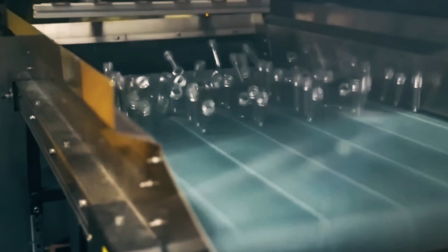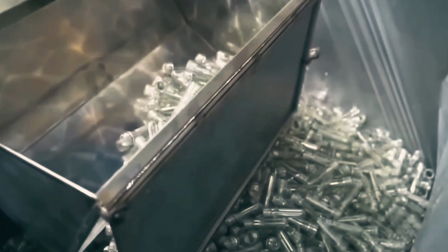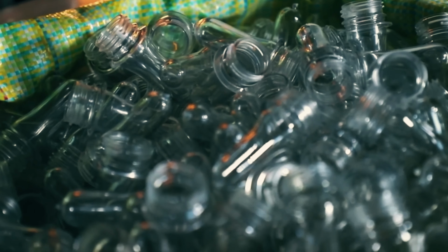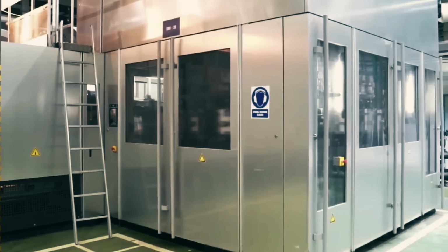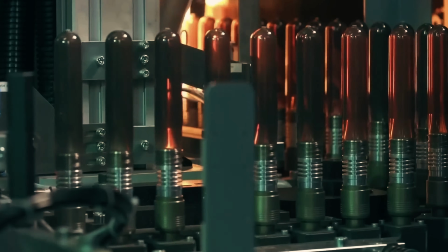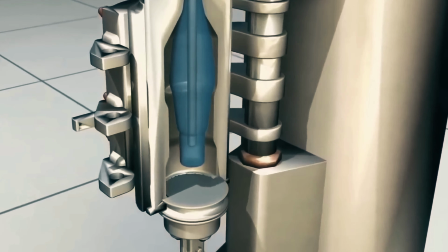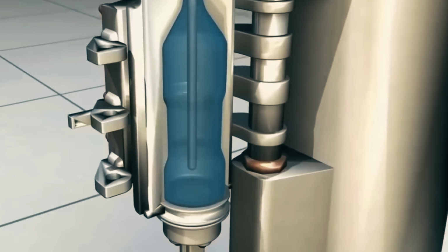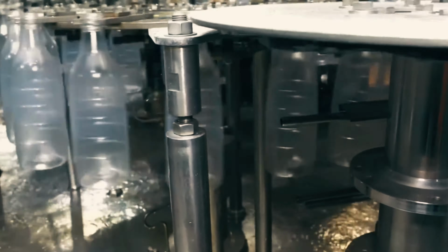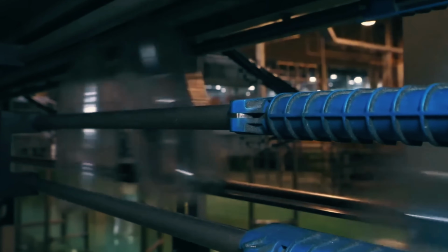They look almost like test tubes with a bottle cap already threaded on top. The preforms are reheated to a precise, narrow temperature window, just soft enough to stretch, but not so soft that they collapse, then blasted with high-pressure air inside a bottle-shaped mold. In under 2 seconds, the softened plastic stretches to fill every corner of the mold, forming the final bottle shape, ridges and all.